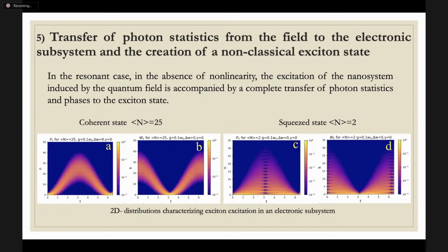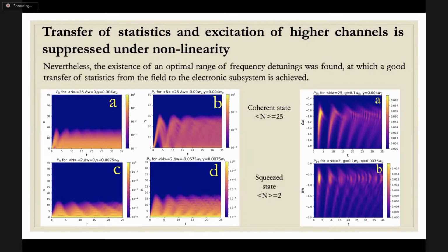Well, interesting results were also obtained under the influence of a quantum field, which is a superposition of Fock states. So coherent and squeezed states were considered, for which the excitation distributions of the electronic subsystem were analyzed. And due to the energy exchange, both the photon statistics and the relative phases are transferred from the field to the electronic subsystem. So the figures demonstrate the formation of photon-like non-classical coherent or squeezed exciton states of an electronic subsystem. And the creation and controlling of such states seems to be the basis for the development of various quantum information algorithms. However, such a situation is possible only in the case of absence of nonlinearity. In the case of nonlinearity, the situation gets worse.